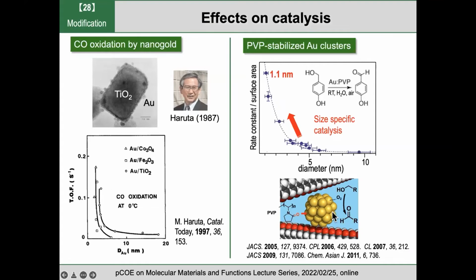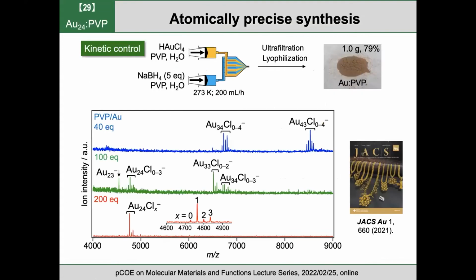Because some of the surface is exposed for chemical transformation when using polymer as a stabilizer. And we changed the diameter of the clusters, and we found that the activity for alcohol oxidation in water is enhanced with decreasing size. So the small clusters actually act as a catalyst for oxidation in water. But in those days, there was some size distribution. The cluster sizes are rather monodispersed, but when we talk about atomic precision, there is a distribution in size. And recently, we successfully synthesized atomically precise clusters protected by polymer.